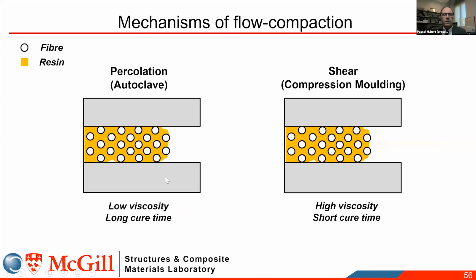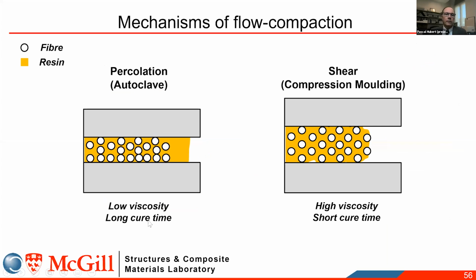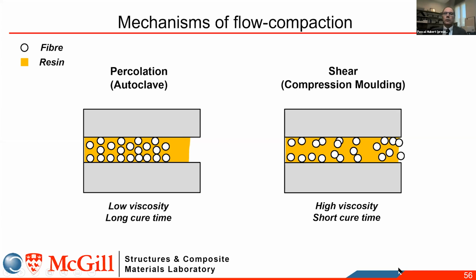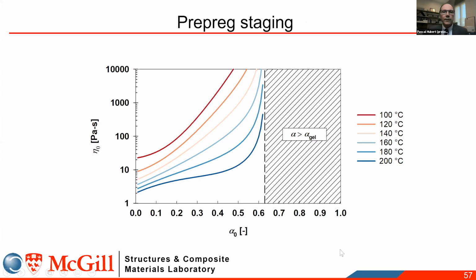That's because the pre-preg was designed for an autoclave process. In an autoclave process, when you apply pressure, you want the resin to flow and wet the fibers. So you want low viscosity of the resin to fully impregnate the part. Then the resin flow will be controlled because of the pressure used in the autoclave and the type of shape that you're making. But when you try to do compression molding, what you really want is for the resin and the fibers to flow together. You want to be in a shear flow mode, which is typical of high viscosity resins. So you want to go from the autoclave to the compression molding process.